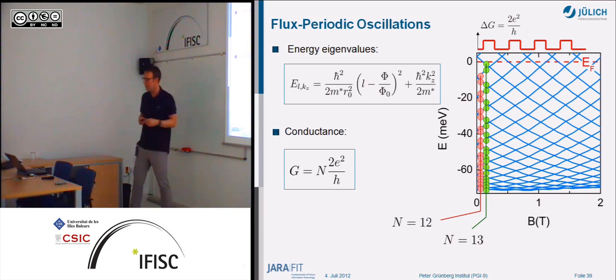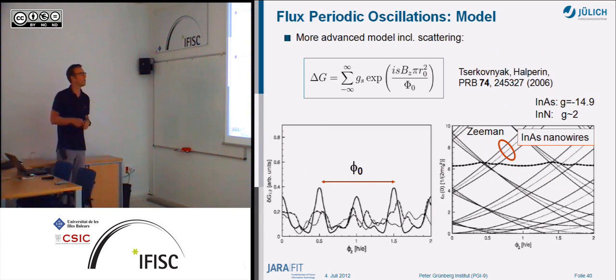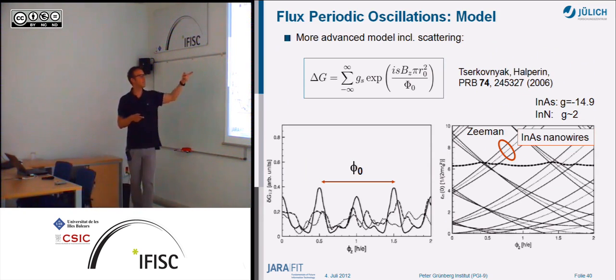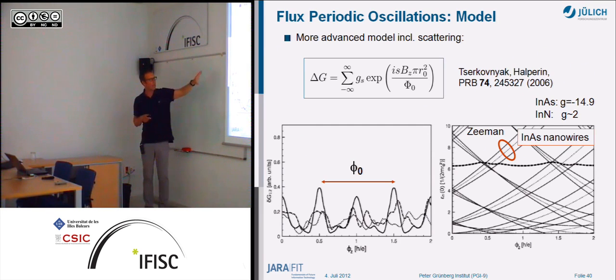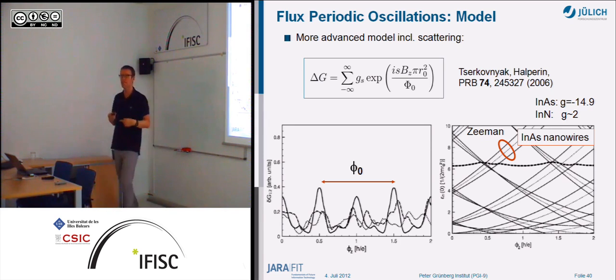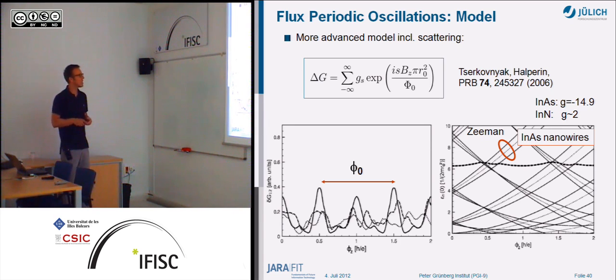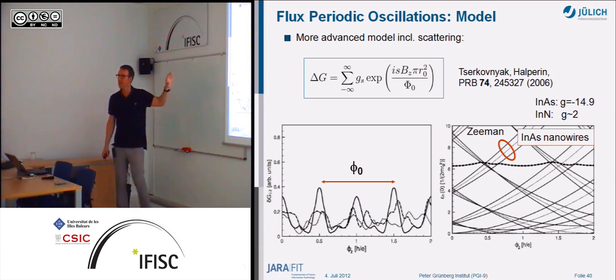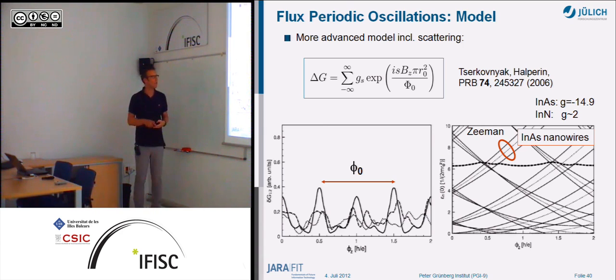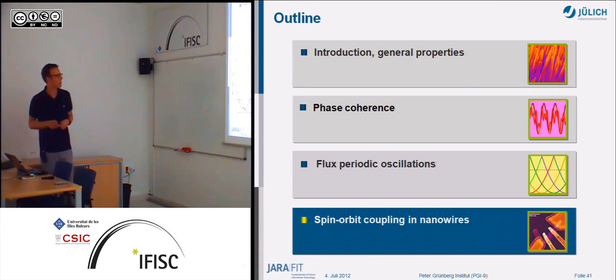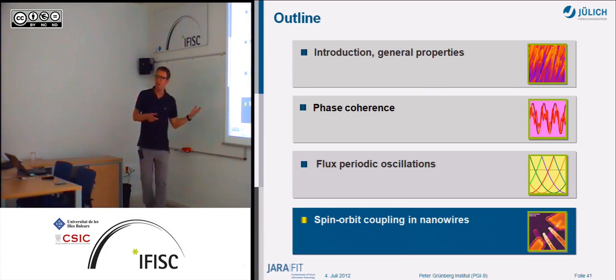Of course, we don't see these steps here. We see some rounding of the conductance, but if you do a more elaborate calculation, as Tserkovnyak and Halperin did, they exactly calculated this kind of system, a tubular system with this angular momentum. You also see that the conductance here is more or less periodic with the magnetic flux quantum. They included scattering, spin-orbit coupling, Zeeman splitting and so on. But at the end of the day, you still get these periodic conductance oscillations. So that's what you get if you look at the charge properties, so the wave properties of the electrons.